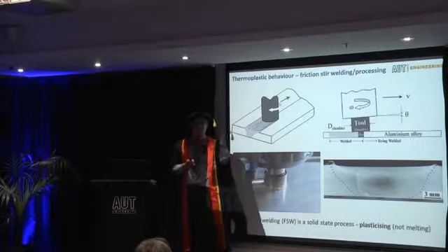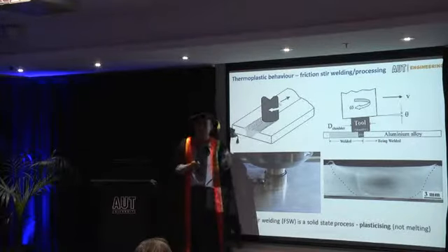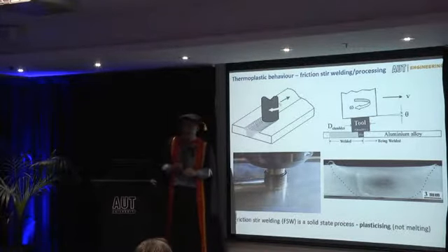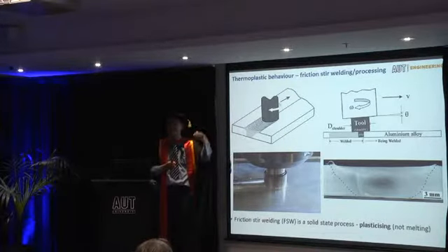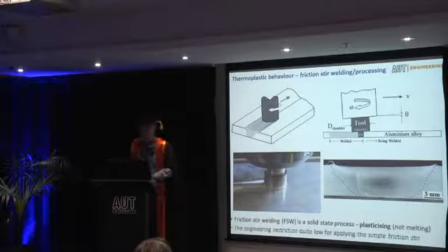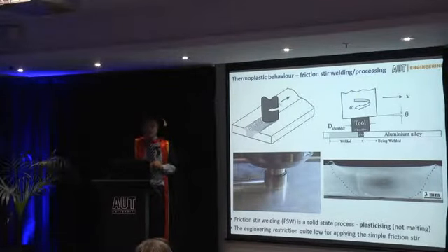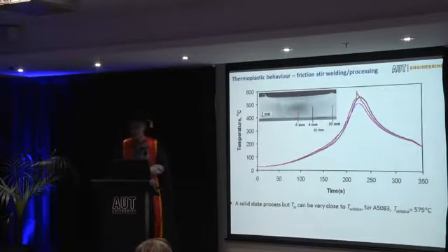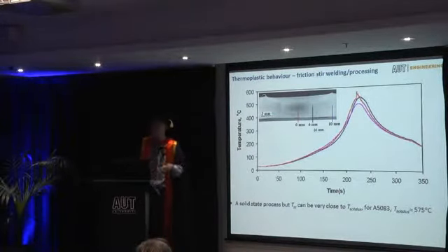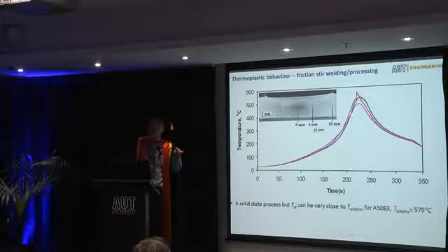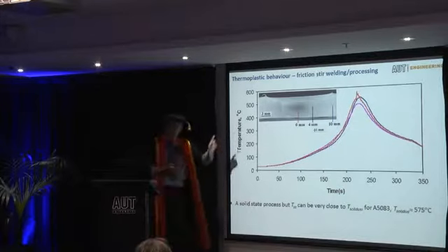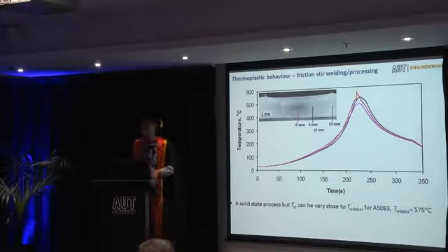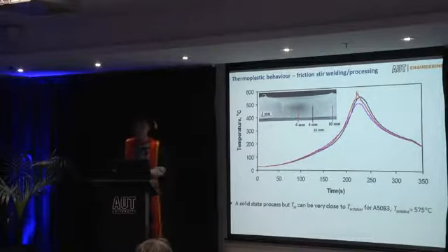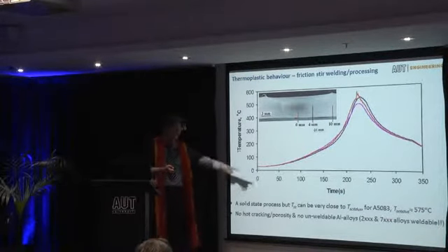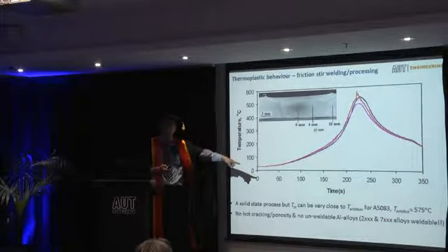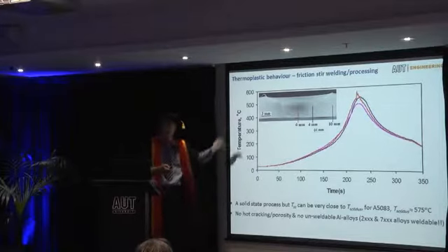Because you involve liquid, you come back to solid, in between you generate a lot of defects. But in aircraft, you certainly don't want defects. This is a solid state process. You don't have those solidification associated problems. And with that, the engineering restrictions of using this are quite low. So this is a demonstration. Again, it's Robbie. Robbie's not here; when he was in his final year as a student, he tested the temperature and figured out it is very close to the melting point, but below the melting point. It's basically a solid state. Because of that, all the so-called 7,000 and 2,000 series alloys that you see on the aircraft, they're all weldable, right?